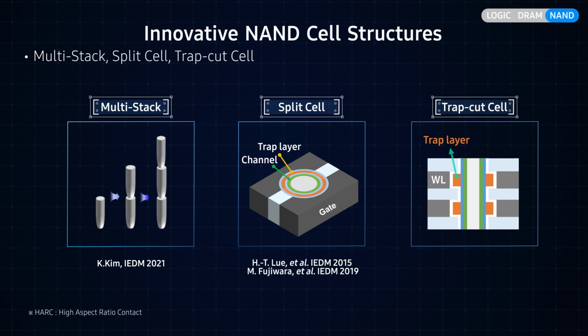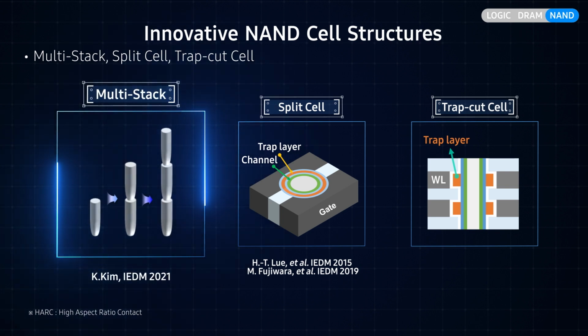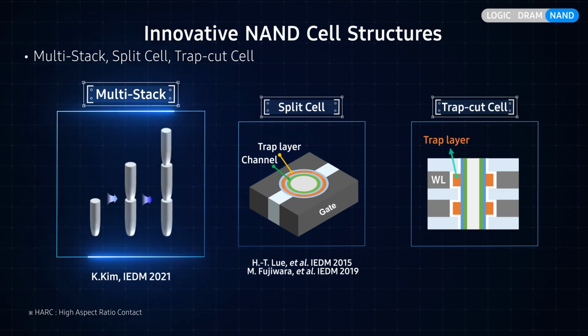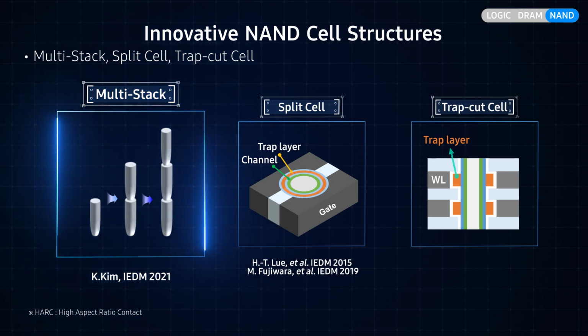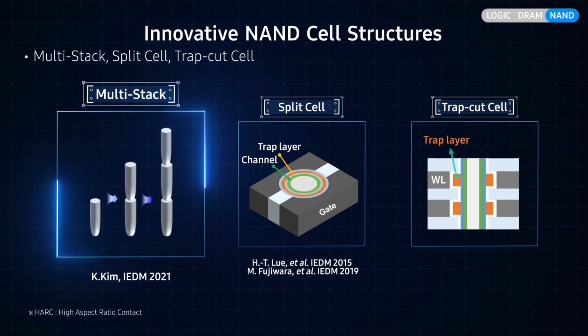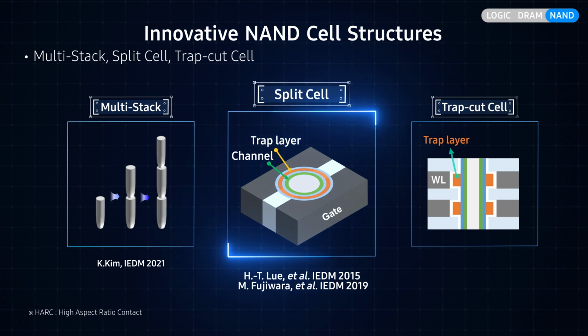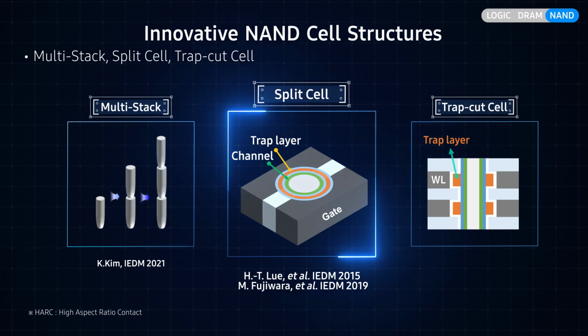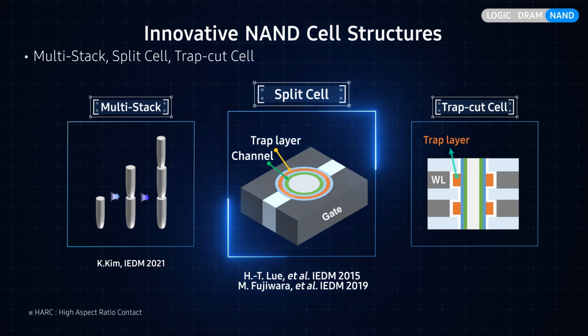There are 3 promising candidate structures: multi-stack, split cell, and trap-cut cell structure. In multi-stack cell structure, we can mitigate the required process capability for high aspect ratio contact etching at the cost of additional repetitive processes. In split cell structure, bit density can be doubled while maintaining total stack height. However, there will be additional hard etching.